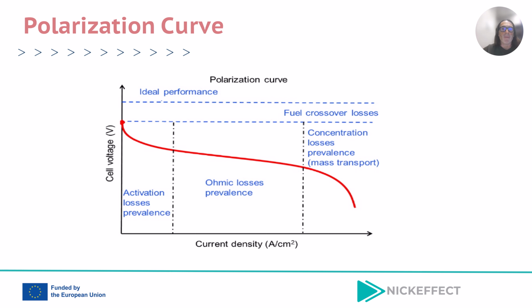Now that we have covered the key components of a fuel cell, like the membranes, the gas diffusion electrodes, catalyst layers, and MEA configurations, let's see how all of this influences the IV curve, also known as the polarization curve. This curve shows how the cell voltage changes with current density. Ideally, we want a flat line. That means constant voltage regardless of current. But in reality, we see a drop due to different types of losses.